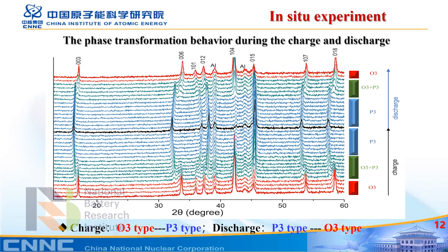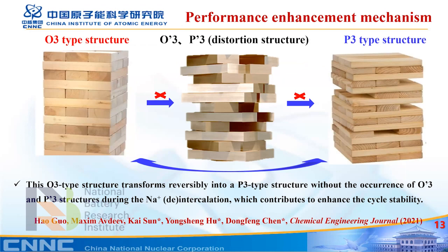Let's see the next slide. Let's use the Jenga again. So during the charge and discharge, there are no other phases like the O3' or P3' phases, only the P3 phase is found. It is believed that the appearance of O3' and P3' distortion structures is very harmful for the cycling stability. Even they can make the structure collapse. So the highly reversible O3 to P3 phase transition is responsible for the cycling stability.